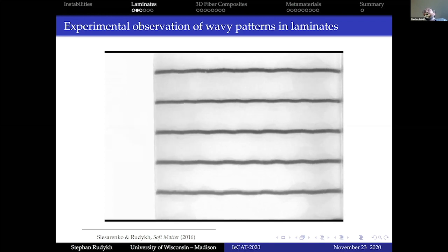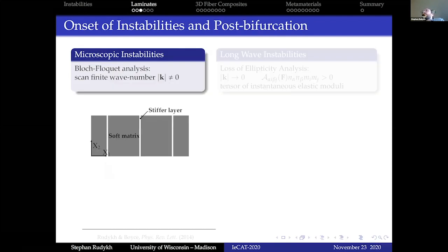and the deformation of these wavy patterns can be very nicely predicted theoretically, and that's where our focus is, and also through numerics. Typically we write lots of equations, and I'll just compress it to mostly this slide, so we can continue without going very deep into the equations. So the analysis, in two sentences, is that typically you use what is called Bloch-Floquet analysis, which allows you to scan through different wave numbers and satisfy certain conditions to identify the instability at this wavelength scale.